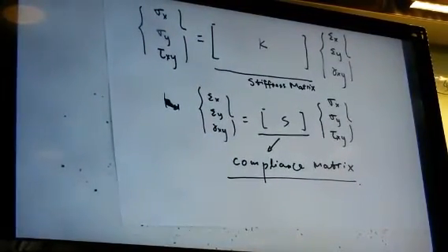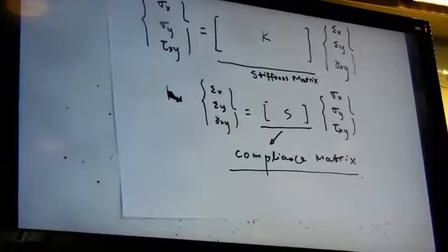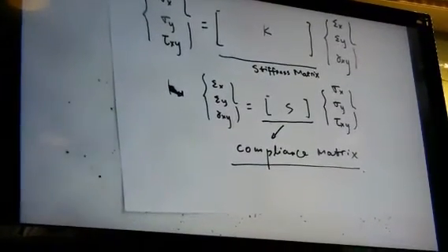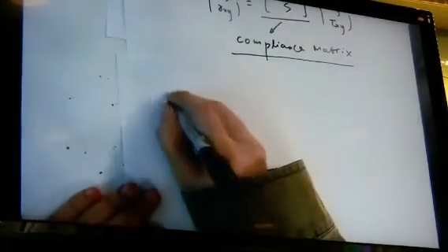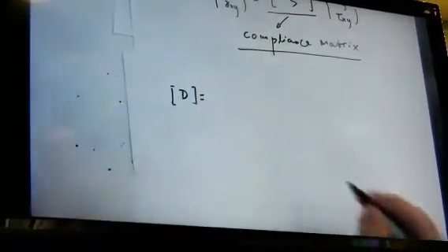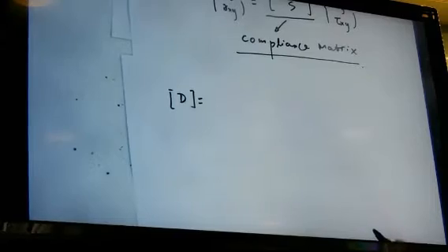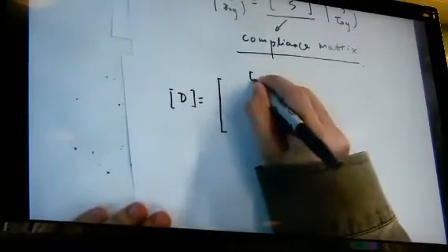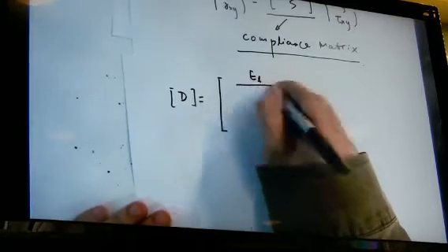How to determine those two matrices? Those two matrices are determined by the inclined angle and the D matrix. The inclined angle is determined by your design, what orientation you want to put your filament. The D matrix is determined by what material you choose for your filament and matrix. The D matrix is this one. I'm going to copy the D matrix again for you.